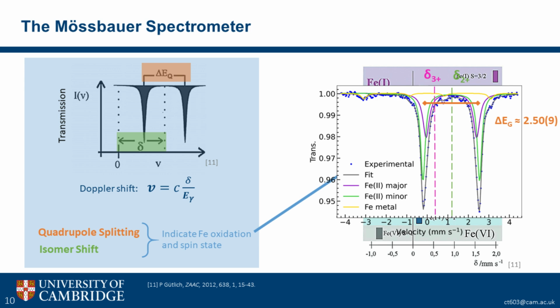iron oxidation states. So now we're going to revisit quickly the spectra that I was showing you at the beginning of the talk for my pristine material. And the quadrupole splitting and the isomer shift tell us that we're in the iron 2+ oxidation state. And for reference, if we were seeing some iron redox in our cathode through charge, what we'd expect would be a shift of the center of the two peaks towards a lower value of about 0.4. So we'd really see the two peaks shift to lower values.